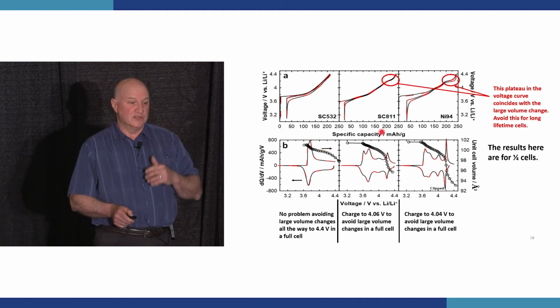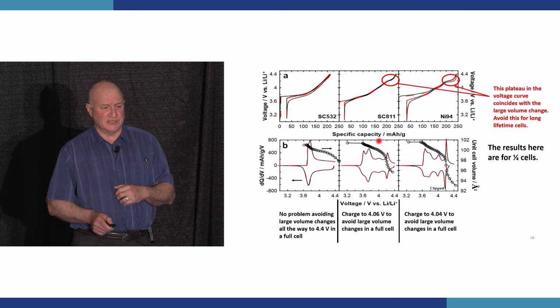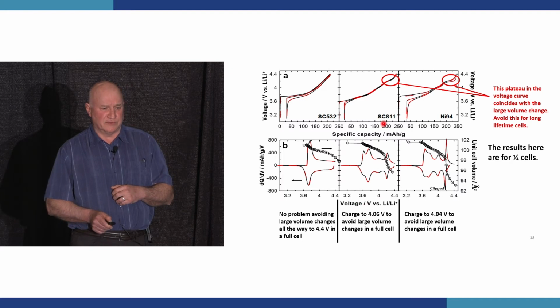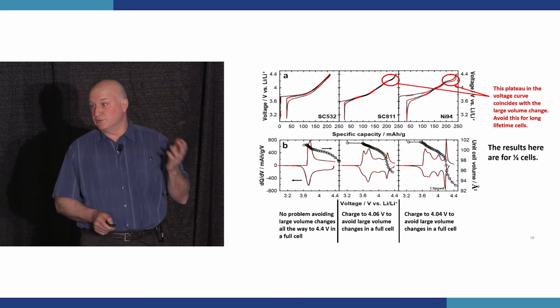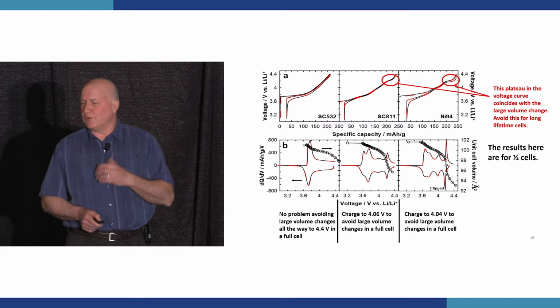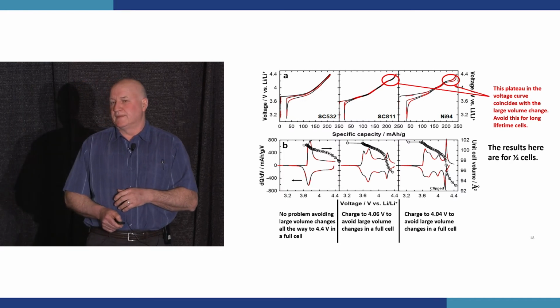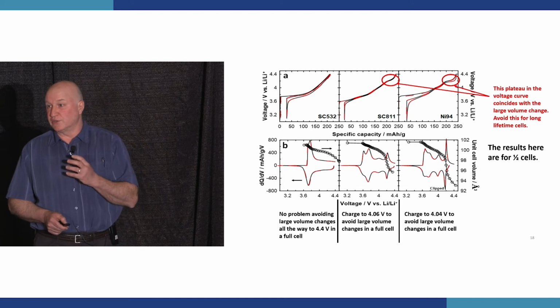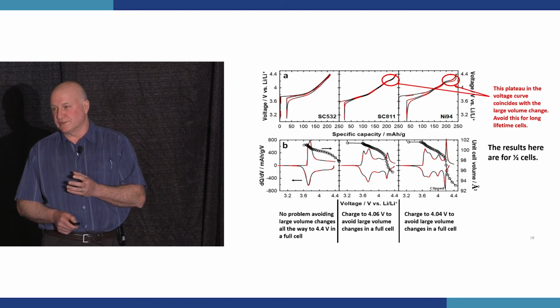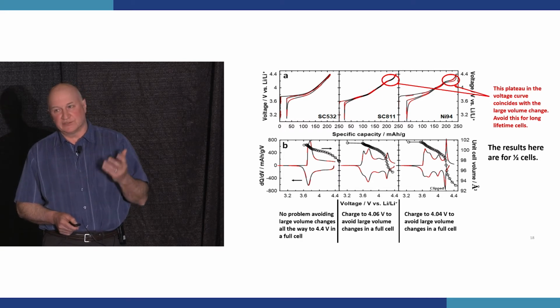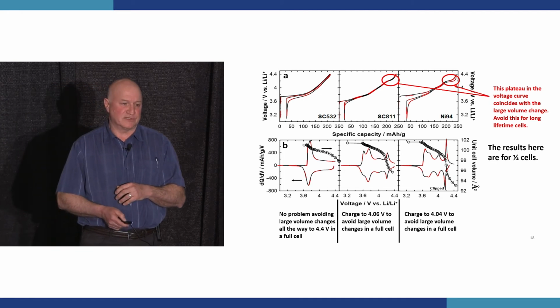So if you want to avoid this large volume change, you would charge a lithium ion cell with 811 to 4.06 volts, and then you would avoid this peak in differential capacity, which corresponds to this plateau, and you wouldn't undergo this volume change. Now, why is this volume change bad? It's bad because it can cause microcracking in the electrode particles, which opens up fresh surfaces on which the electrolyte can react. And then that leads to impedance growth and all kinds of other problems, as I'll show you here.